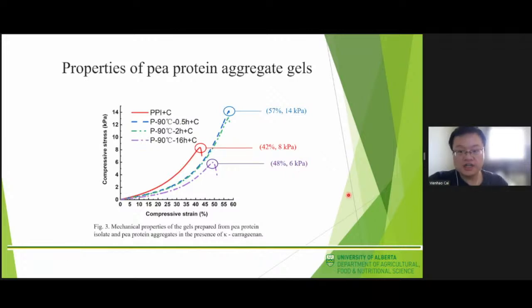The further increased gel mechanical property by using pea protein aggregates could be partially attributed to the significantly increased surface hydrophobicity on the protein aggregate surface, rendering them more active building blocks to form hydrophobic interactions to reinforce the gel networks. Reduced surface charge on protein aggregates compared to the untreated protein might also contribute to strong gel formation, because the reduced repulsion could facilitate the development of attractive force among aggregates.